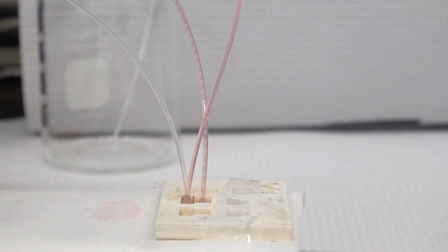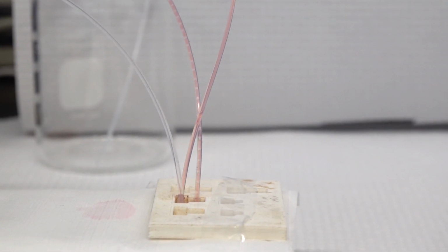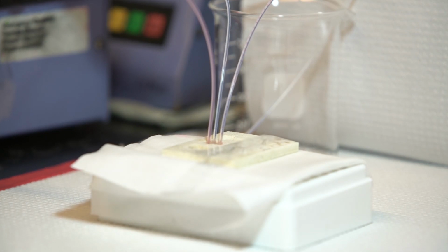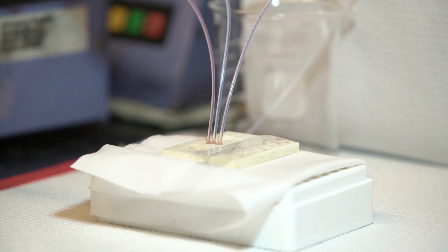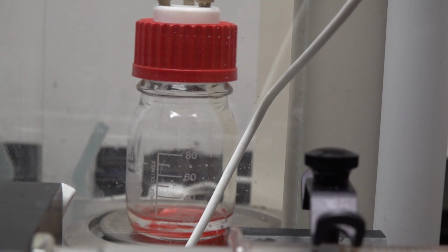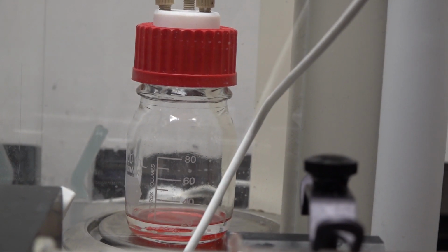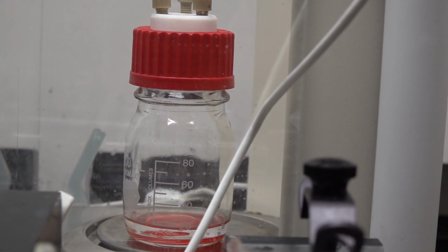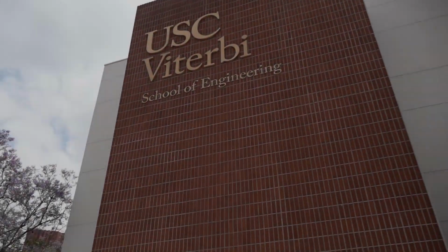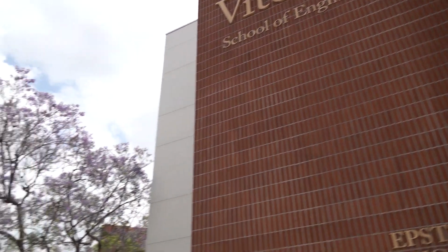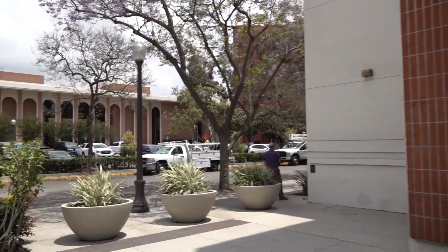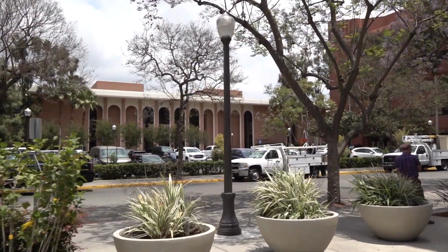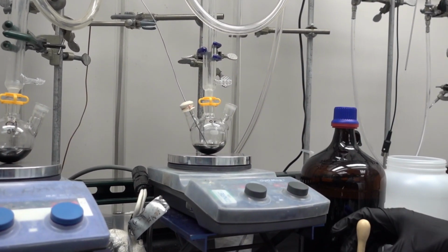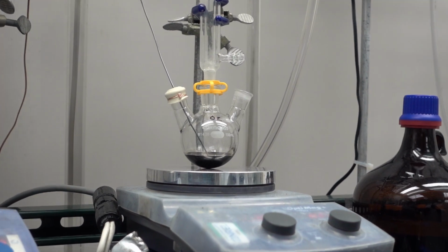This allowed us to make over 18 grams of molybdenum carbide nanoparticles in continuous flow in a day, compared to 100 milligrams in a single batch reaction. This equates to more than 370 grams of 5% catalyst in a 24-hour period. Non-traditional scaling approaches, like the continuous flow synthesis of carbide nanoparticles being pioneered at USC, are helping to bridge the gap between the lab-scale batch syntheses and engineering-scale application of these materials.